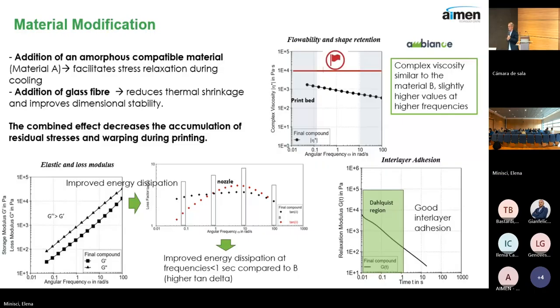warping. And finally, on the right is the relaxation modulus curve. So we see here that the curve fits perfectly within the Dahlquist region. This anticipates also a good interlayer adhesion, so a good quality part.